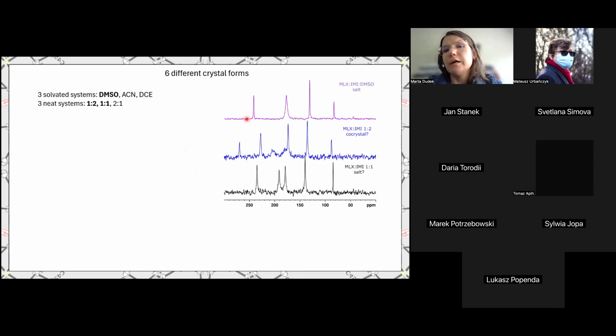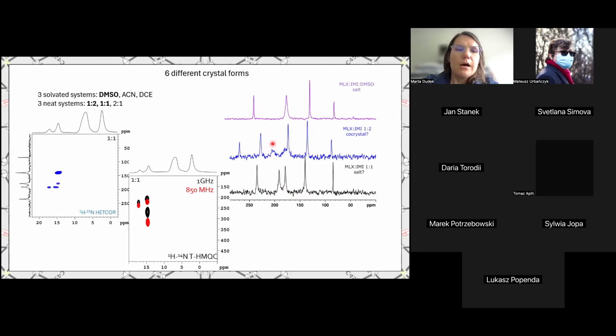nitrogen 15 resonances. So this is, for the sake of comparison, a nitrogen 15 spectrum of a salt, salt solvate of meloxicam imidazole, which was determined through single crystal X-ray diffraction. So from this, we assumed by comparison that this should originate from a salt and this one from a co-crystal. But note that here are very broad additional yet unexplained signals. So first, we are looking at the high field NMR measurements for one-to-one system.